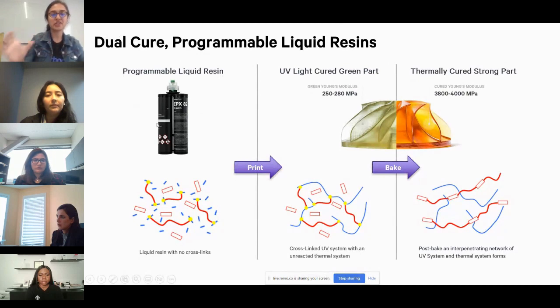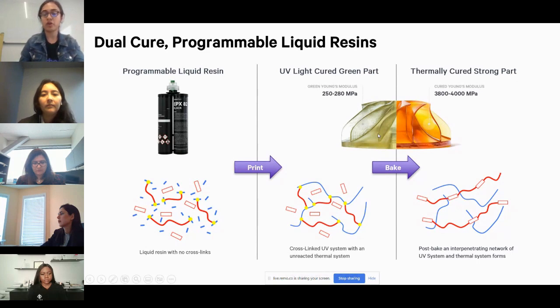Essentially, we have arranged the polymer chains and the end blocks in a specific way. In this example, I'm talking about polyurethane resins, where, as I mentioned, during 3D printing the UV curable chemistry is activated when we shine the UV light, and we get the formation of a UV cured polymer network, which has some of the thermally curable parts still trapped within it. This is the green part I was showing during the 3D printing process. Once the part is removed from the 3D printer, we wash it and spin it, and then it is ready for the second step, the baking step, which activates our thermally curable chemistry. Then we form an intertwined polymer network of the UV cured polymer network as well as a thermal cured polymer network, which gives the final 3D printed part really good mechanical properties.